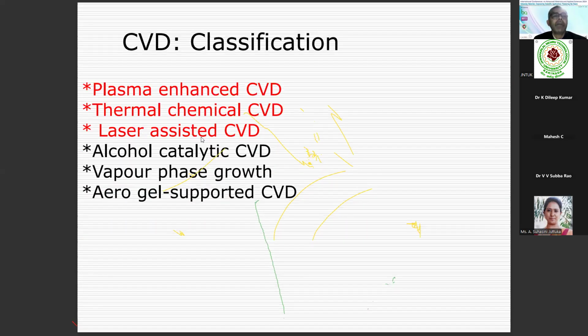Now CVD is defined in many ways. You can say plasma enhanced, where you generate a plasma to crack this carbon. Thermal means just thermal heating of more than 700 centigrade, which you can produce in any oven, to crack these gaseous carbon molecules into reactive carbon molecules. Maybe laser assisted CVD, where a strong laser is put on that one, and the plasma or thermal is replaced by laser light. Then alcohol catalytic, where a catalyst is made by alcohols, which may move this reaction very fast, and you can get a very good yield of carbon nanotube.